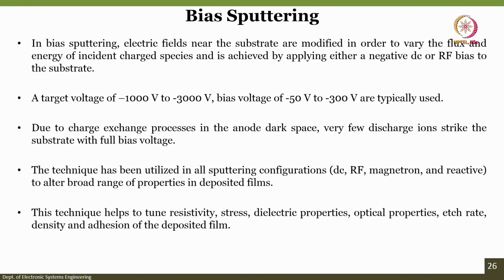Now, if we apply a bias, in bias sputtering, the electric field near the substrate is modified in order to vary the flux and energy of incident charged species, and this is achieved by applying either a negative DC or RF bias to the substrate. So, if you keep the target voltage around minus 1000 to minus 3000 volts and the bias voltage about minus 50 to minus 300 volts, then you can have better sputtering, and due to charge exchange processes in the anode dark space, very few discharge ions strike the substrate with the full bias voltage. The technique has been utilized in all sputtering configurations, whether it is DC, RF, magnetron or reactive, to alter a broad range of properties in the deposited film.